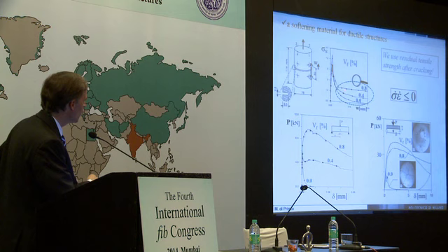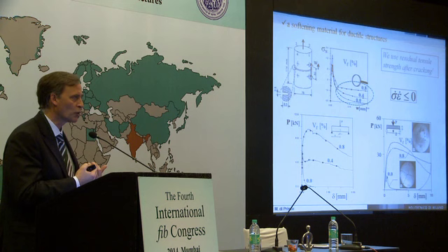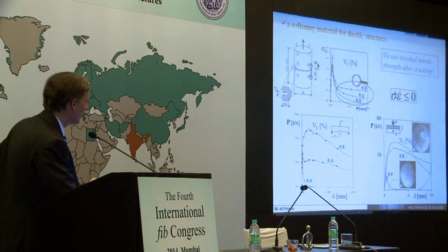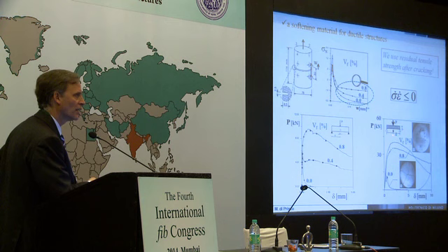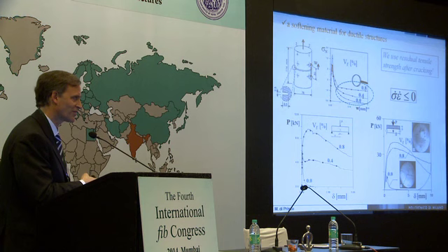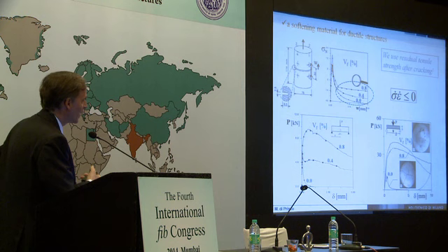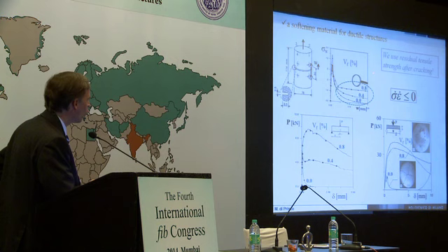So this residual strength is nothing when used in uniaxial tension, but becomes very important if you have just bending, or even if you have a circular plate supported on the perimeter. That means that if you increase the redundancy of your structure, you can profit as much as possible from the residual strength offered, so by the toughness offered by the material. And so we have to consider that always the main contributions come after cracking.